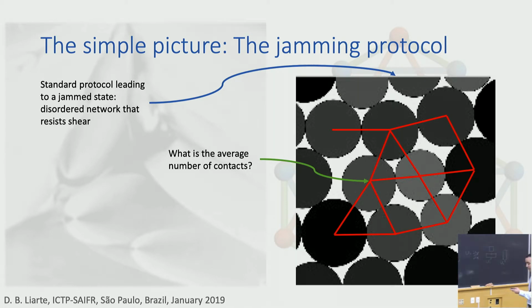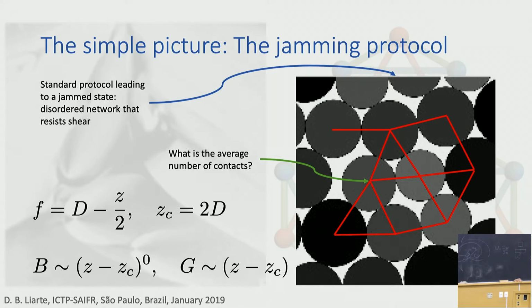And there's an argument that has been given by Maxwell that if you count the number of floppy modes, the number of modes of deformation that don't cost any energy, you can use an accounting argument, and it's given by the number of degrees of freedom, which is just the dimension here, minus the number of constraints. And the number of constraints is this average number of contacts divided by 2, because you have a double counting here. These two disks have the same constraint. So when the number of floppy modes is 0, based on this very simple counting argument, you reach mechanical stability. So that's the critical, the isostatic point, and I'd like you to remember this name, isostatic, because I might use it later.